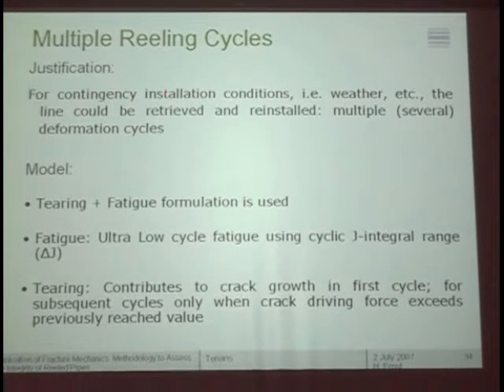Now, multiple reeling cycles. As I said, contingency installation conditions, weather, etc., may require that the line be retrieved and reinstalled. So imagine we put the pipe to the higher deformation and then release it to the second, smaller cycle. But if we have to retrieve it, we have the line going again through the smaller deformation, the larger deformation, and then when we start it again, another smaller deformation. So we go from 2 to now 5 cycles, 5 deformation cycles, and if we repeat that, we keep on adding 3 each time. So we can have a pretty complicated history of deformation cycles, so about 10 or 12 is not very uncommon. In this case then, what we need to do is to include the fatigue part.